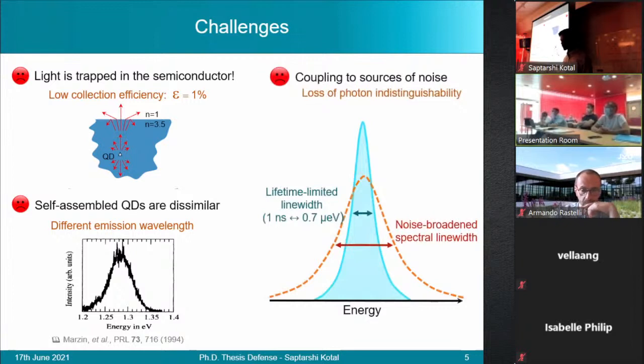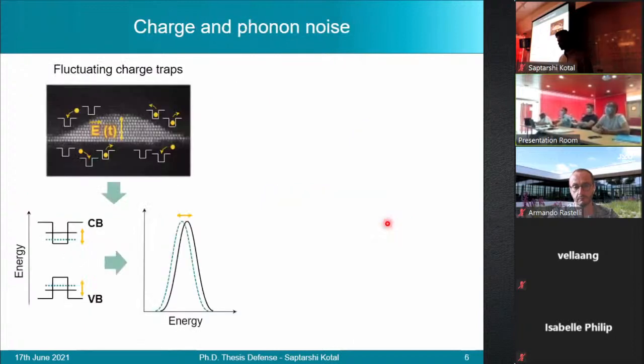Then the quality of the emission is further hampered because the quantum dot tends to interact with its surrounding. So there are sources of noise in the surrounding which make the line width of the emission broaden compared to the radiatively limited line width of the quantum dot. The dominant sources of noise in our systems arise from either charge fluctuation in the surrounding or phonons that come from lattice vibrations.